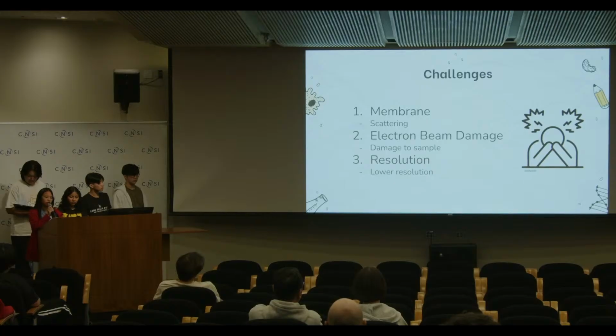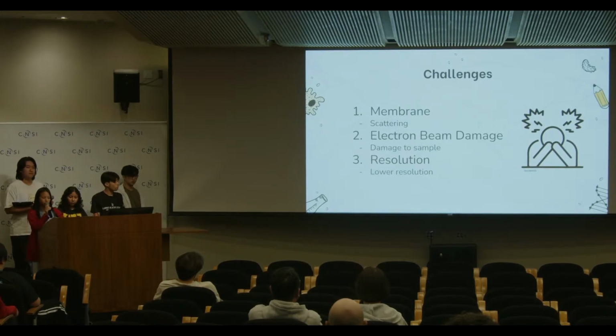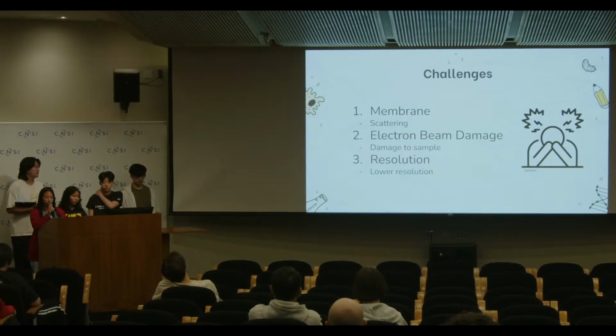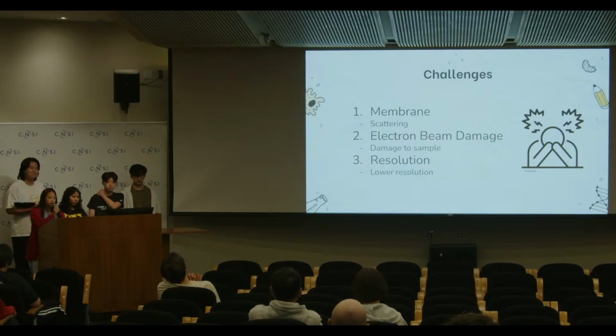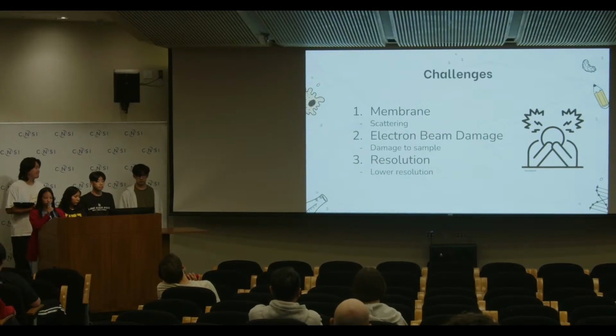So here are some challenges. The membrane of the liquid cell acts as a barrier to isolate the liquid from the high vacuum. Isolation is crucial because high vacuum environments can cause liquids to evaporate quickly. However, the need for a liquid environment leads to many other challenges. The first challenge is the membrane, which must be thin, tough, and high transmittance to withstand the pressure difference and allow sufficient electron beam penetration and signal detection. Thicker membranes lead to increased electron scattering, which would degrade the resolution and contrast.